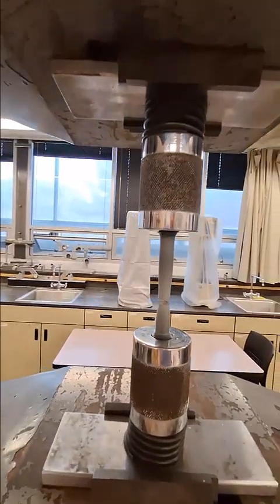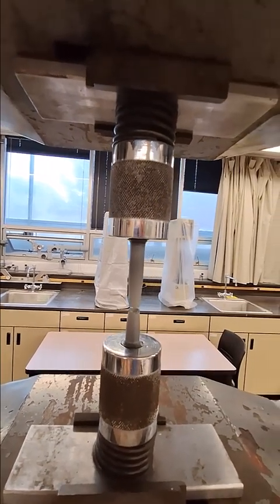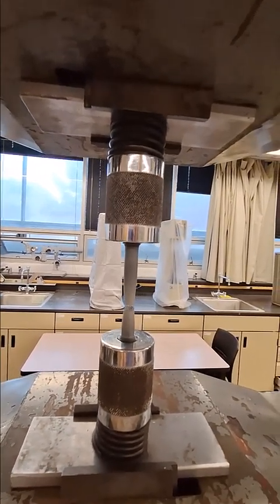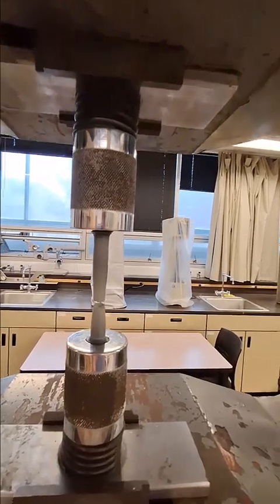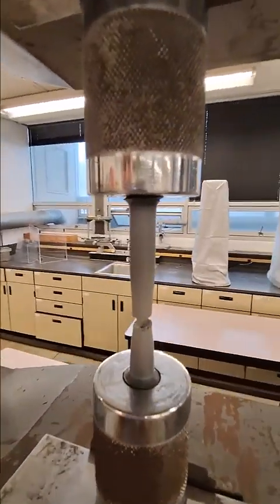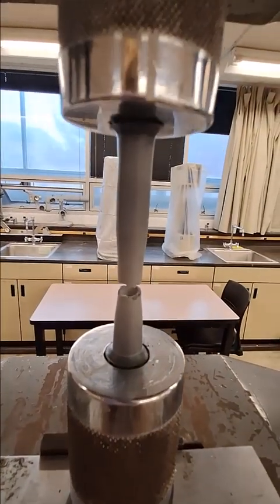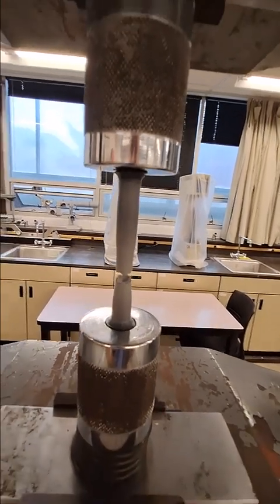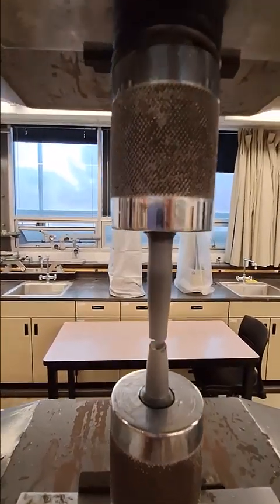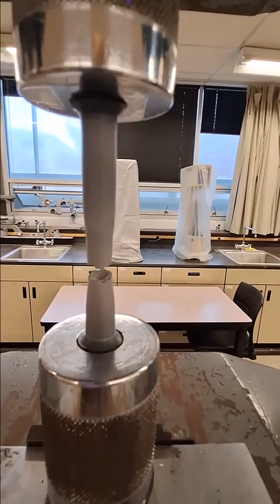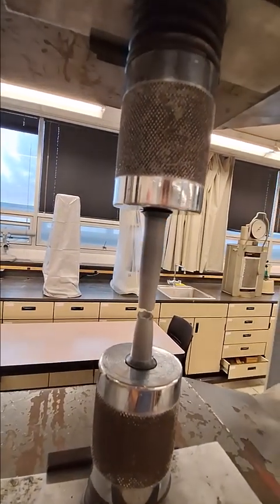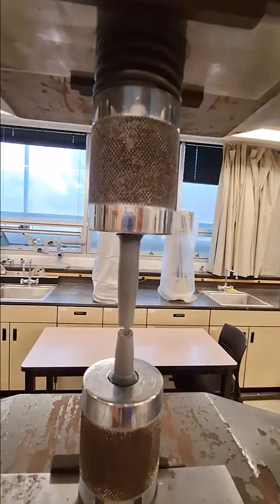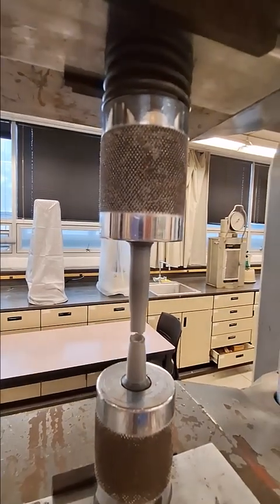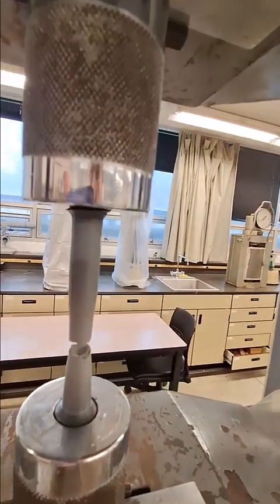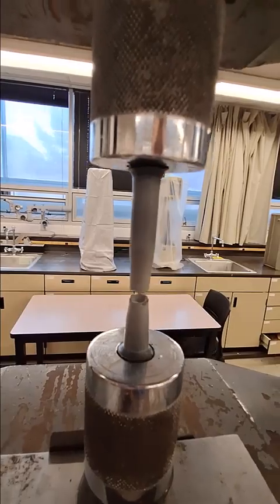So we'll let it keep going because we want to unscrew it. But you can see that fracture right here. And it is indeed still a ductile fracture, especially compared to metals and ceramics. But for polymers, you'll see that is a fairly brittle transition, even though we still see the neck and all of those good things. So this is our polystyrene fracture.